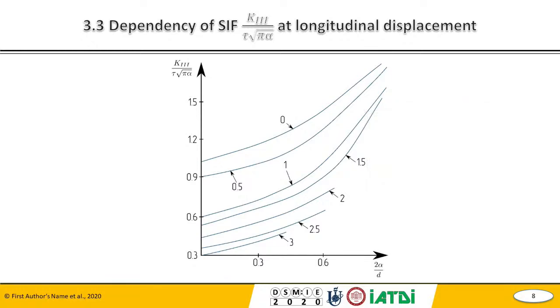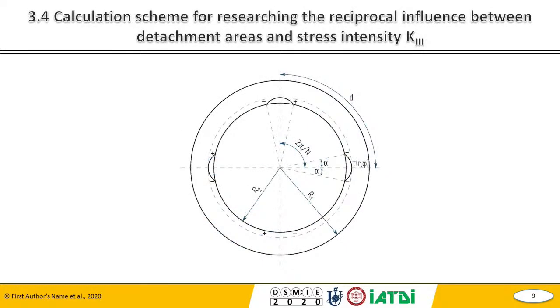Slide 9. The analytical model for the study of the relationship between the relative distance of the detachment sides and the stress intensity factor is shown on this slide. It should be noted that the stress intensity factor can reach significant values without disturbing the equilibrium state, since the distance d increases and the coefficient 2 alpha d decreases.